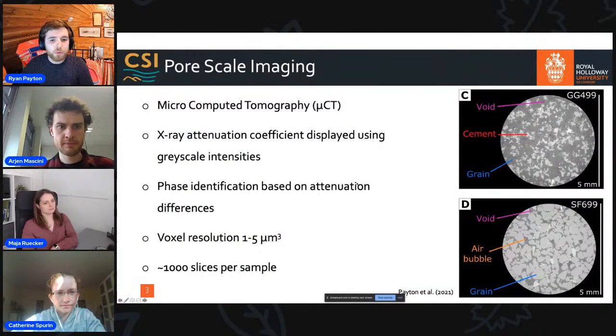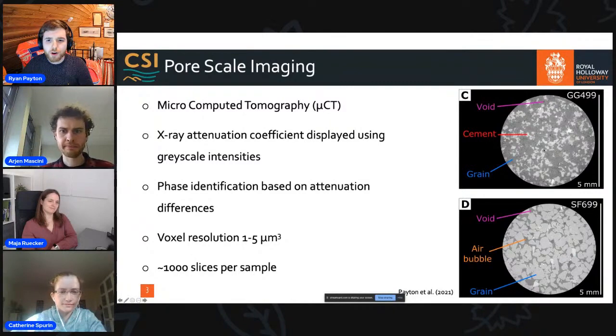So I also use some of the techniques which you were just hearing about. Predominantly, I'm using micro-CT. This is where we see X-ray attenuation displayed in grayscale, where the paler features are the grains and the darker areas are the pore space. Ultimately, segmentation of these phases allows us to make measurements related to the solid material and the void space fraction. The images we get from this give a voxel resolution of between 1 and 5 microns, depending on the sample. And typically there are about 1,000 slices in a given sample in order to reconstruct a 3D volume. These are a couple of examples here. This is a really nice porous sandstone, and this one is a really horrible cemented sandstone with very limited porosity in it, which I'll show you a bit more about.